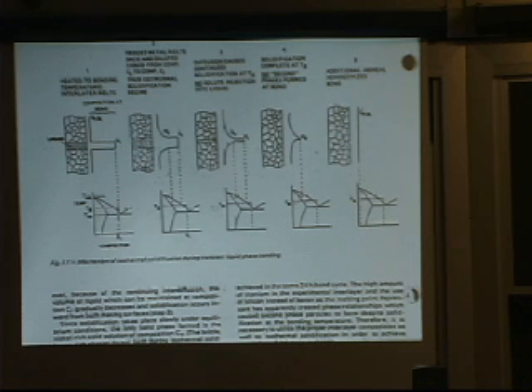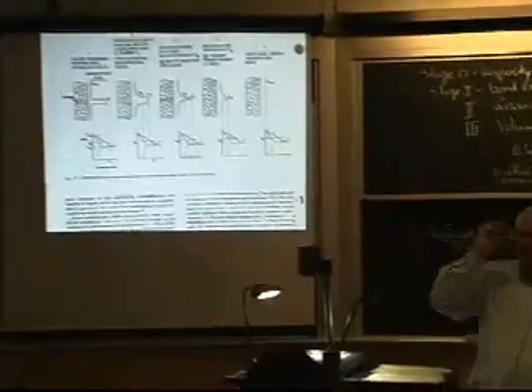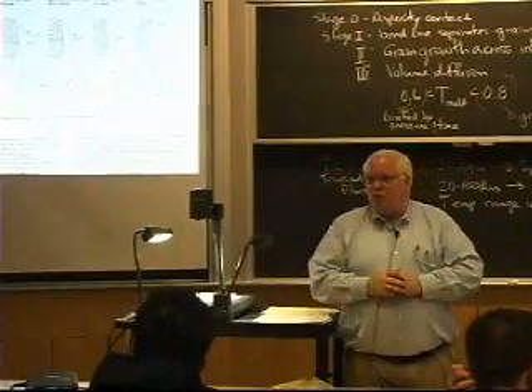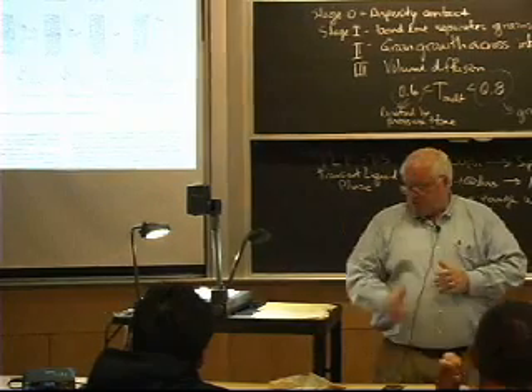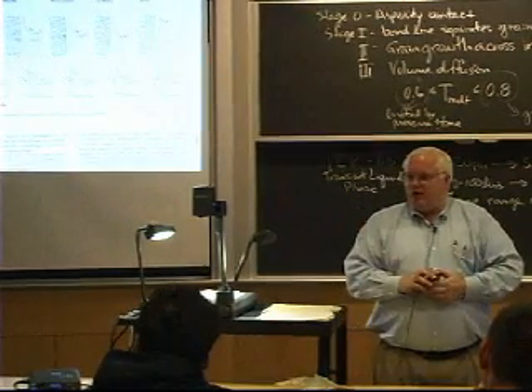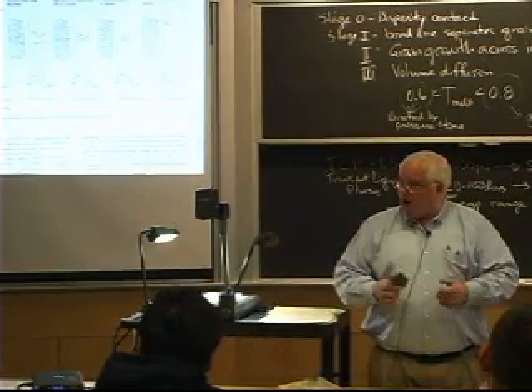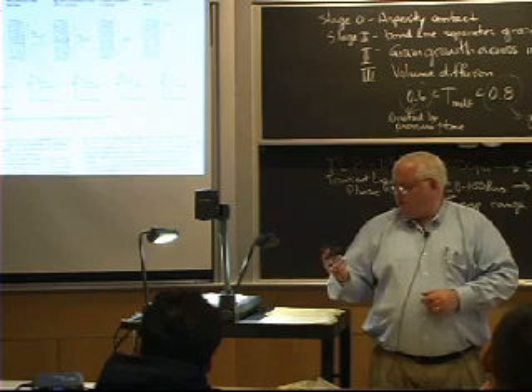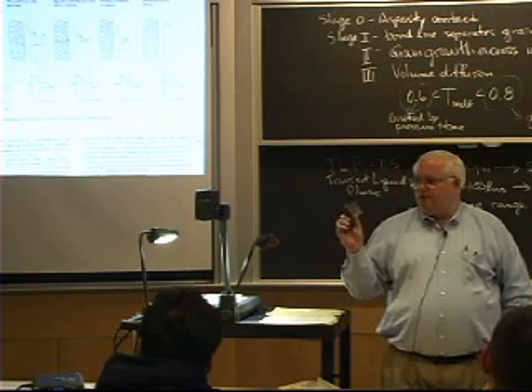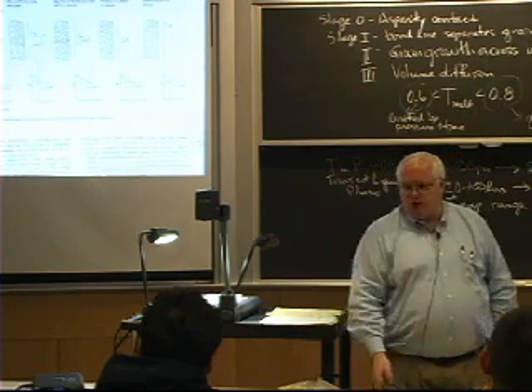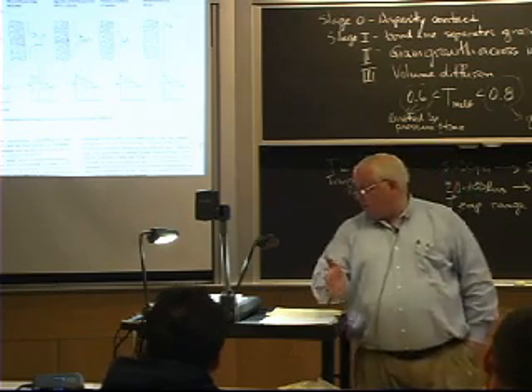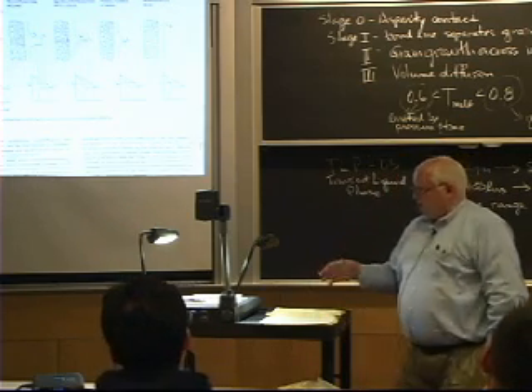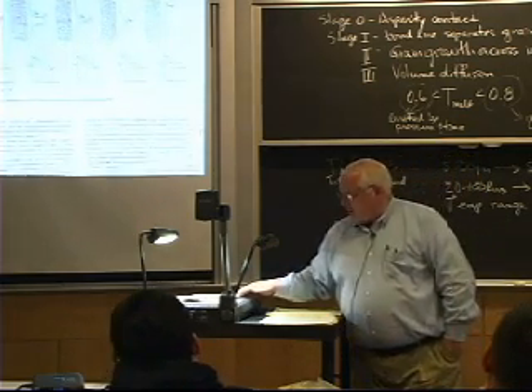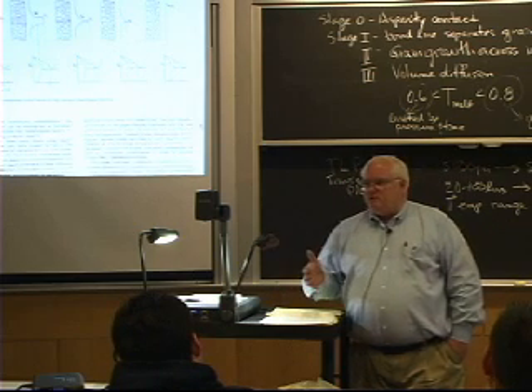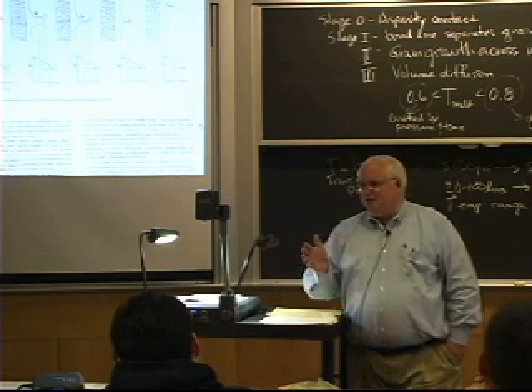So I can put a nickel boron alloy in between here. And lo and behold, did you know that some of the most widely used nickel-based turbine blade brazing alloys are nickel boron alloys? I've always thought that these people came upon transient liquid phase diffusion bonding, whether it was Rohr in '56, General Electric in '62, or Pratt & Whitney in the later '60s, because someone left the part in the brazing furnace too long and diffused away the boron.